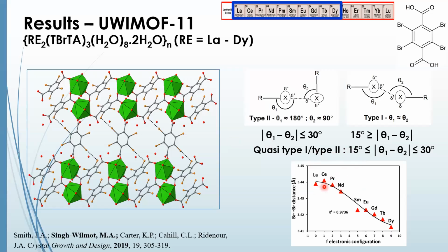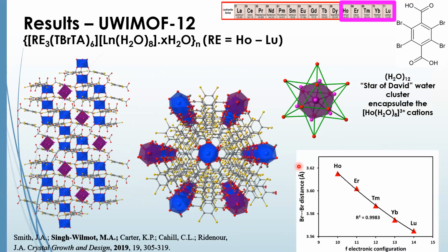And I'm showing you what we found when we studied the tetrabromo structures. You can see here the bromine to bromine distances as we vary the lanthanide size. We go from lanthanum, large, to dysprosium, small. The bromine to bromine distance gets smaller. So there's a relationship between the size of the lanthanide and the strength of the interhalogen interactions in these MOFs. And there were some other very nice structures with the tetrabromide.